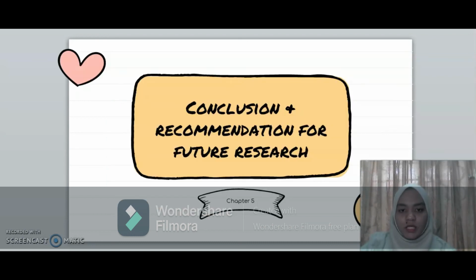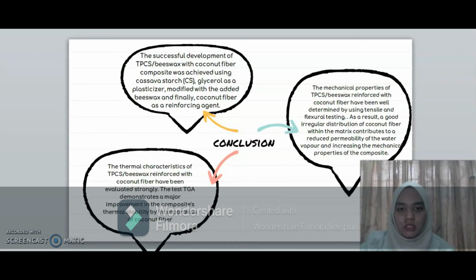Chapter 5. Conclusion and recommendation for future research. Conclusion. Objective 1. The successful development of TPCS and beeswax with coconut fiber composite was achieved using cassava starch, glycerol, and coconut fiber. Objective 2. The thermal characteristic of TPCS beeswax reinforced with coconut fiber has been evaluated. The TGA test demonstrated a major improvement in the composite thermal stability by incorporation of coconut fiber.